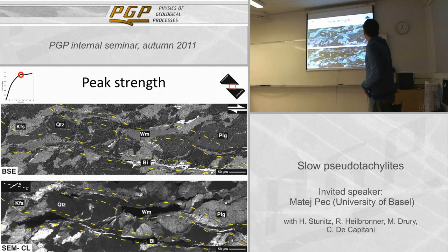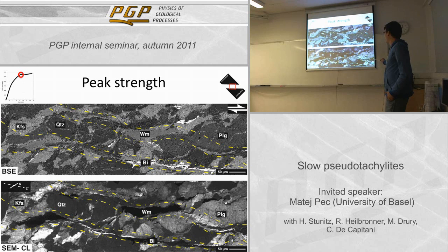We can also see that within those slip zones, very often there are extension fractures that are associated with the putting of the experiment back to room conditions. So, sorry, I have to say this again. Basically, once we end the experiment, we have to take it out from 500 MPa confining pressure to room pressure again, and this leads to the extension of the zone.